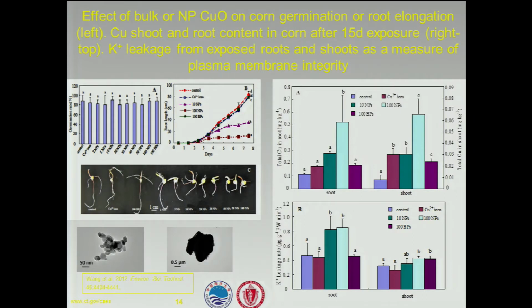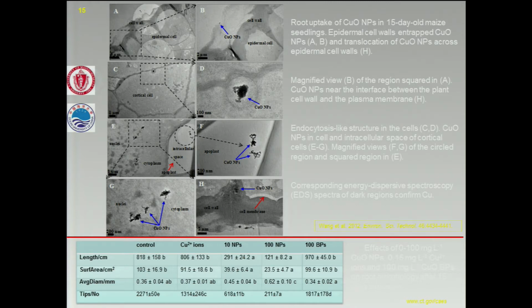This experiment was the effect of copper oxide nanoparticles on corn germination and root elongation. What we were trying to see is how many of the seeds germinate when we put them in a solution of copper oxide nanoparticles. We also found that toxicity shows over there. The number of seeds germinating is less for the copper. Here is the total amount of copper that is present in the root. So, the root uptake of copper nanoparticles, we see what is happening to the cells.